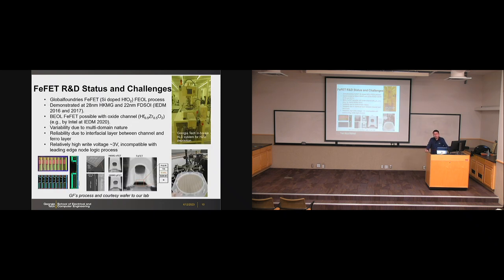Of course, there are many challenges with this new technology. And here I just show some status in terms of the industrial development of this technology. GlobalFoundries pioneered the industry development with silicon doped hafnium oxide in their front end of line process. They have successfully demonstrated 28 nanometer high-k metal gate and 22 nanometer FDSOI FeFET. And also, we can integrate FeFET in the back end of line process. For example, you can stack that on top of the silicon using some oxide channel. This has been reported by Intel recently with some semiconductor oxide channel with the FeFET as a back end as well.